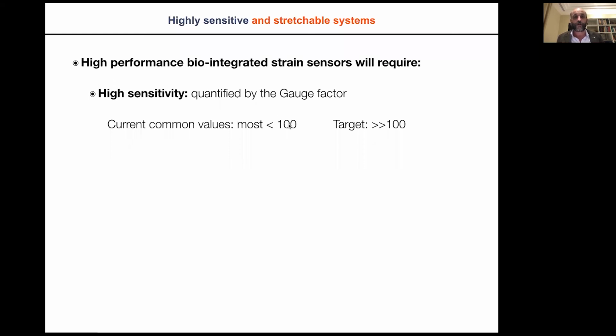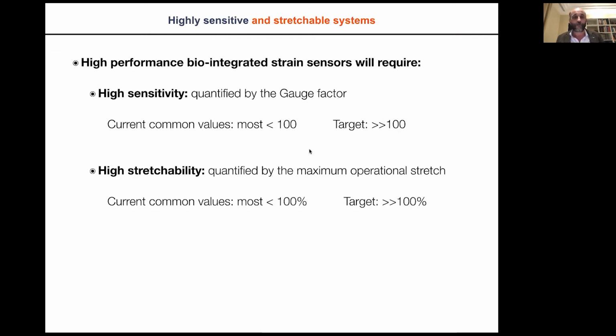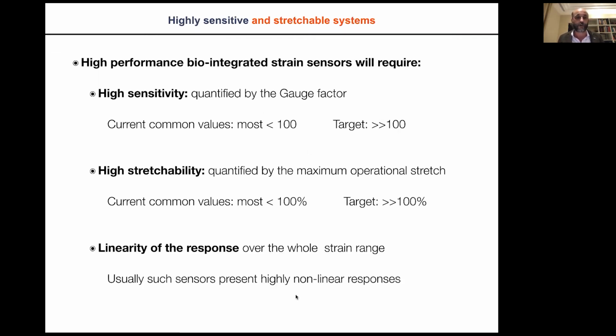So that means a gauge factor that is well above 100, while most of the sensors have a gauge factor around 2 and well below 100. We wanted to get something that is highly stretchable, something that can go well above 100% of stretchability for the application that we wanted to target, and with a linear response. That means something that is not completely nonlinear, where you have a regime of strain that is easy to measure, and then it's difficult to measure the rest. So these were the three requirements that we had for the technology at the beginning.